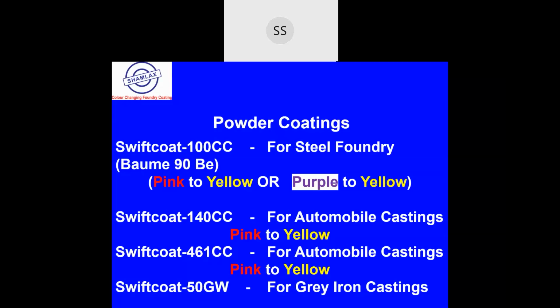And for the automobile castings, you will have actually a thick base of the aluminum silicate based coatings, where the dilution, depending on the foundry, has to be done, maybe around 25 to 30% or even 35%. Water addition has to be done in the aluminum silicate based coatings. And then you can dilute it to around 40 Baumé and then use it.